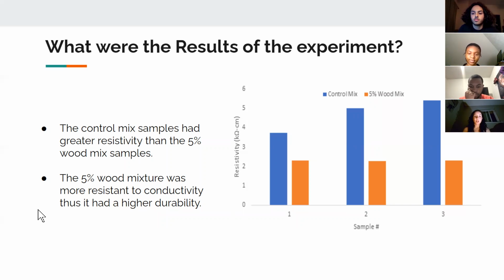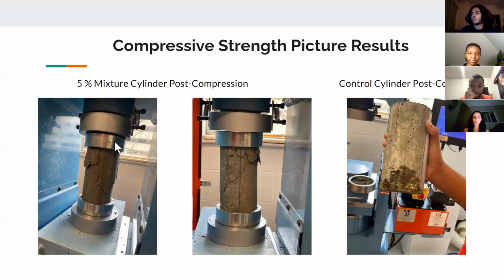In the next slide, you can see some photos of what the cylinders looked like post-compression. So for the first two that you see on the left, the 5% mixture showed a certain degree of post-compression fractures. And then for this last photo on the right, the control cylinder post-compression, you can see a lot of the voids that we noticed within the cylinder before the compression, and then the fracture point at the bottom.